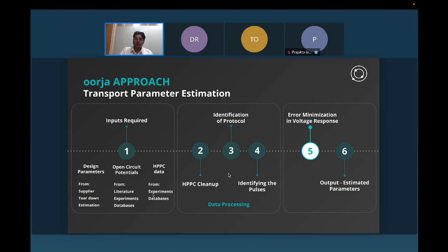That requires a cleanup of the data before we can make use of it for optimizing these parameters. So the process after we have uploaded the HPPC data together with the other parameters is that first we perform the cleanup of the HPPC data, and then for the HPPC data there are certain important sections one needs to look at to understand the cell response, and that is where we have automated this process and we identify these protocols. And once we have identified the HPPC protocol, we also identify the pulse regions, because those are the ones which show us the cell characteristics. And then once we have pre-processed all this data, it is ready for the optimization of these parameters to match the voltage response that we see experimentally to what we see from the simulations.